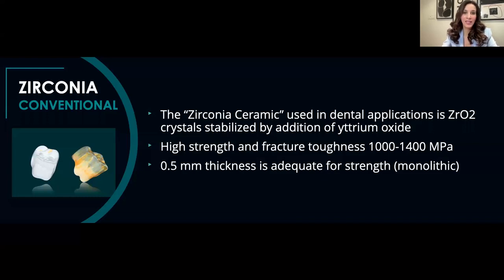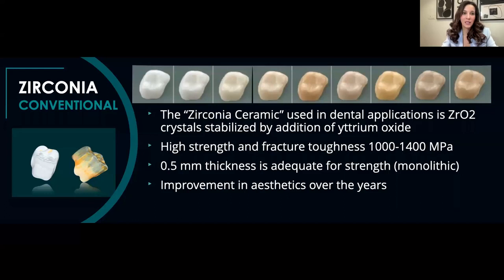And historically, as I mentioned at the beginning of the presentation, the zirconia was not very aesthetic. And you can see in the slide above, it was very white. So when I first started providing patients with zirconia restorations, they weren't necessarily the most aesthetic restorations, but that has certainly improved over the years. And initially, to offset that, we'd have a zirconia core, which was very strong, and then layer feldspathic porcelain, but we would see delamination of the porcelain. So that's not what we do anymore. We're doing more monolithic materials.